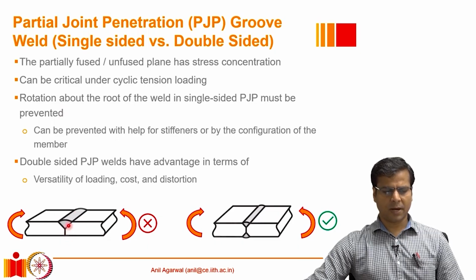Also, one must be careful that when we provide a single-sided partial joint penetration groove weld, the one that is shown for example here, and if it is subjected to a loading in such a way so that this root at this location is subjected to large tension force demands, or if it is subjected to a situation where it leads to some kind of stresses which produce opening of this weld at this location. For example, the type of loading that is shown here will produce a moment demand at the root of the weld. Such type of loading has to be prevented in single-sided partial joint penetration welds. However, in a double-sided partial joint penetration weld, if weld is present on both sides, a moment which is applied like this does not produce a very large stress demand here, because there is a lever arm available, and therefore such kinds of welds are more versatile. They are able to carry different types of loads.